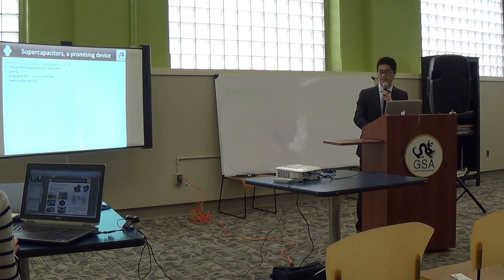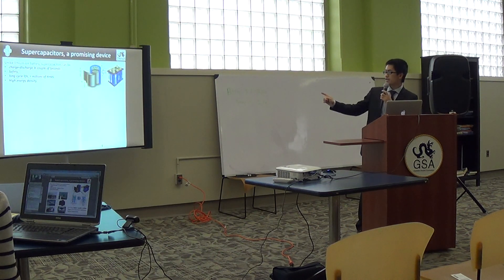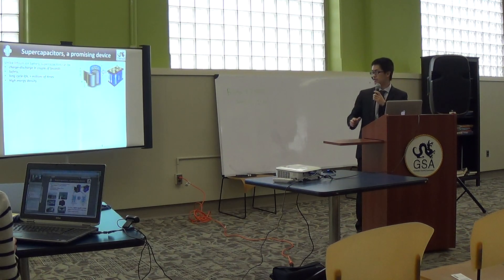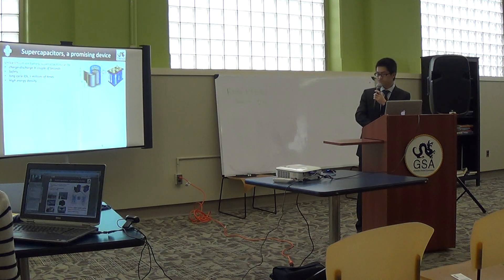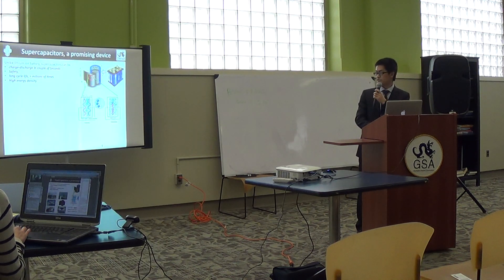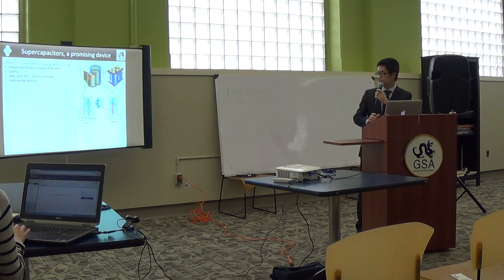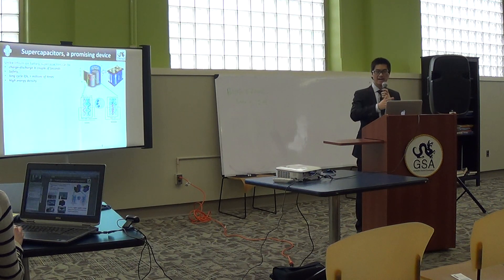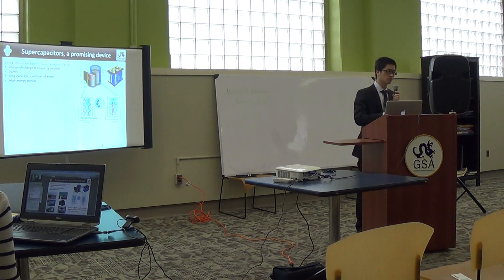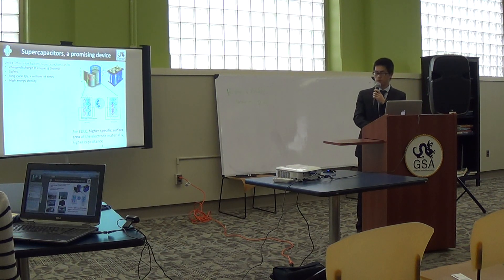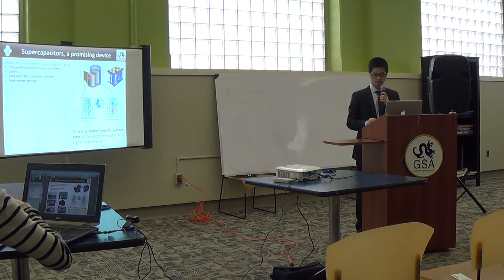You may wonder what a supercapacitor looks like. Here we have four supercapacitors in series. If we look inside one, it has a separator and positive and negative electrodes. Looking further, the electrode is composed of nanomaterials that are highly porous. When charging, negative ions and positive cations go to the respective electrode areas. When discharging, the ions go back into the bulk electrolyte. We want high specific surface area, which corresponds to higher capacitance.